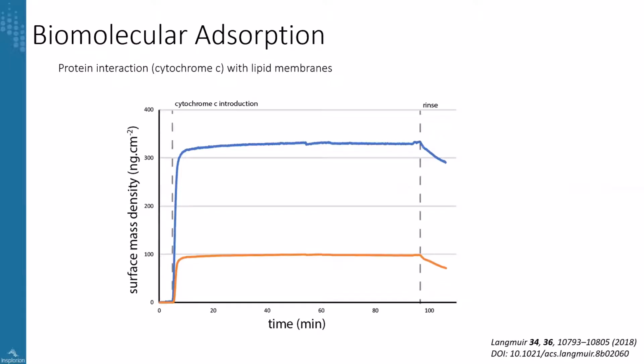Once the lipid bilayer is formed, you can go a step further and you see how molecules interact with that bilayer. In this case, the protein interaction with the lipid membranes, it was cytochrome C was used to see how it would incorporate into the membrane. In this case, the Acculite instrument was used. So other than the NPS data, which is shown in orange, you can also see the QCM data, which is shown in blue. And you can see there is a big difference between the mass calculated with NPS and with QCM. So this is a good example to see how much water is attached to the cytochrome C that is going into the membrane.